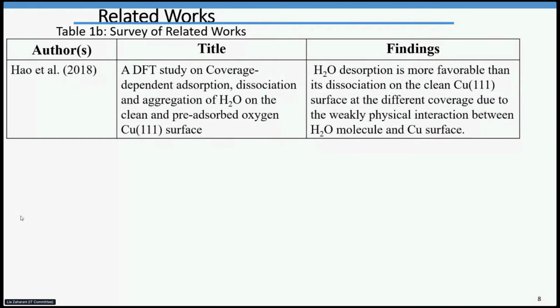Hao et al. 2018 did work titled Density Functional Theory Study on Coverage-Dependent Adsorption, Dissociation and Aggregation of Water on Clean and Pre-Adsorbed Oxygen copper surface. The water desorption is more favored than its dissociation on the clean copper surface at different coverage due to the weak physical interaction between the water molecule and copper surface.